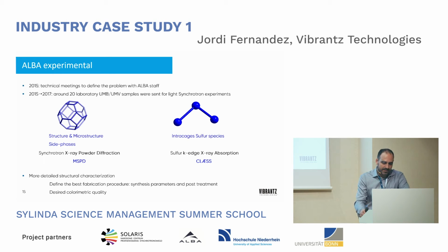And then the second part is to study the sulfur species. For this, we go to CLAESS to run sulfur K-edge X-ray absorption to do a speciation of the sulfur species in the ultramarine pigments. The idea was to have a more detailed structural characterization of our pigments, to define first the best fabrication procedure to enhance the properties of our pigments and to increase our margins and so on, and then how to obtain the desired colorimetry by a combination of these different chromophores.